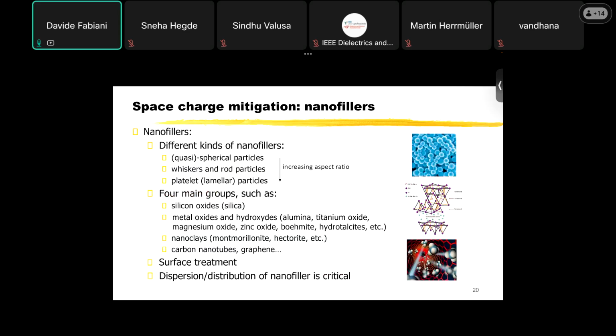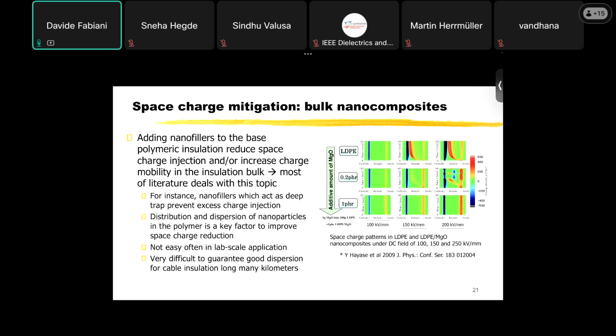For instance, we can have spherical particles, whiskers, platelets, and you can see here a large group of fillers that can be used: silicon oxide, metal oxide, and for instance, magnesium oxide is very much used to reduce space charge accumulation, nanoclays, or also carbon nanotube, graphene, and whatever.